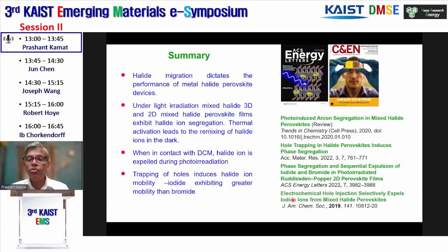And with that, I would like to summarize what I showed so far. Halide migration dictates the performance of metal halide perovskite devices. Again, this is an ongoing issue, and people are coming up with various treatments and removal of surface defects to improve the performance. But even if a very small fraction of this process remains, it can create this issue. We also showed that the iodine can come out of these materials under light or heat. Again, it may be a very small fraction, a thousandth of a percent efficiency, but still it can cause long-term damage.